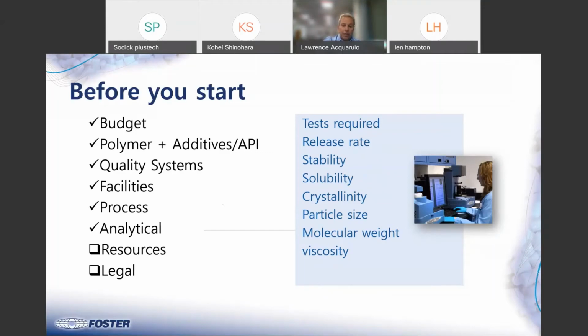Certainly managing the molecular weight, we can measure that, and the inherent viscosities of the material. Now we do that two ways. The IV, which is a soluble viscosity when we're doing the bioresorbable. And we also have the capillary rheometry, which is a melt, and we can get the shear rate viscosity curves, and that's going to be important for designing the tooling.